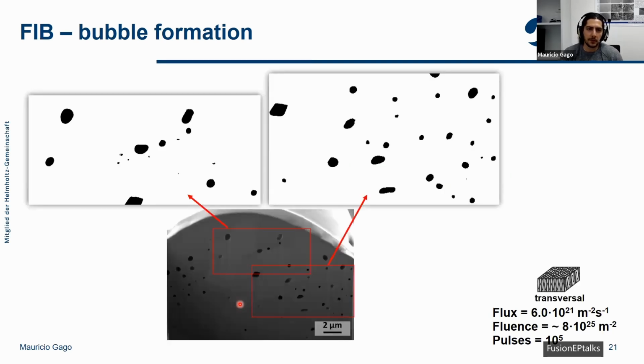And we can expect the size to be even larger with a higher plasma flux. As we saw, the pores also increase in size. So I would say that most probably the size of the bubbles also grows underneath the surface with a higher fluence.